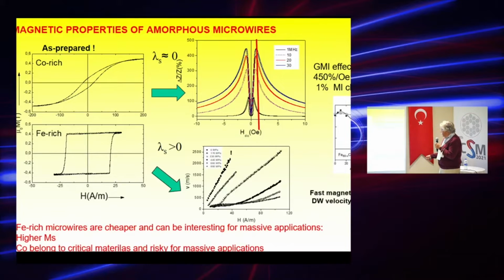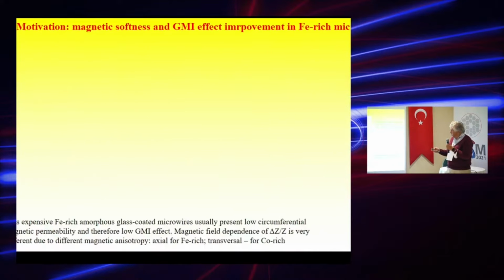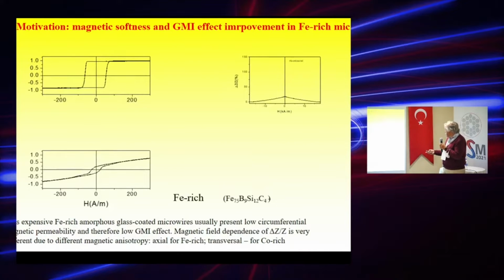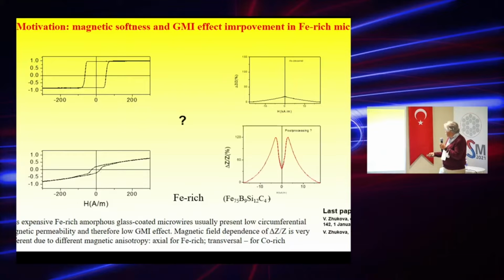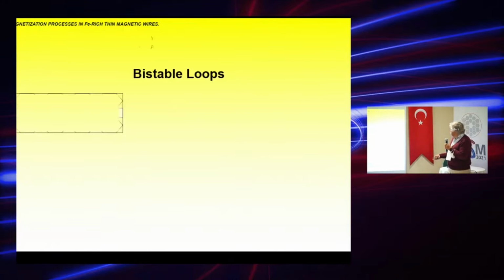Iron-rich materials are usually interesting for very fast domain wall switching, with velocity up to 2.5 kilometers per second. But as I already mentioned, iron-rich is much cheaper, and cobalt belongs to the critical materials. Therefore, there is a demand to look for some post-processing to improve the magnetic softness of iron-rich materials. This is the main motivation of this work. So the question is whether we can find a way to change this hysteresis loop to that one, and improve the giant impedance effect from this very poor performance typical for iron-rich materials, because the permeability in this low field region is quite low, to that one. We tried, and recently we published a few successful attempts, and this is the content of my talk.